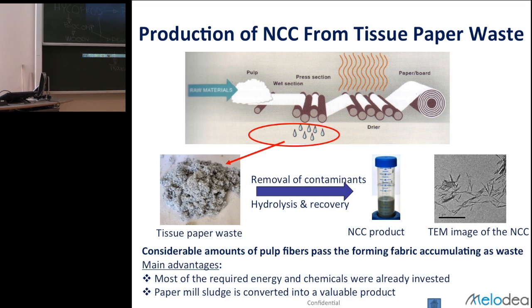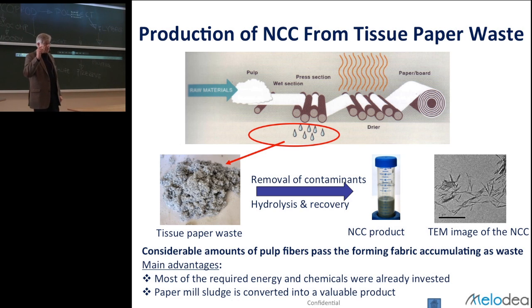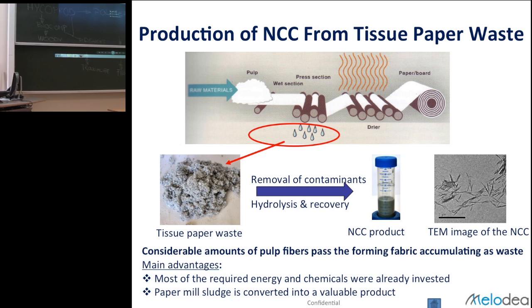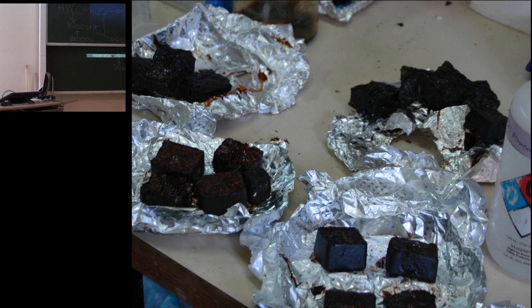So I take that, put it in my mixer, the drink mixer, to make it smaller. And when the drink mixer can't make it smaller, I use sonification, ultrasound. With the sonification, I can make it so small that it turns transparent. It's still a gel inside, but it's completely transparent. And it happens in minutes. And it is that transparent gel that I freeze, take away the ice, and have my foam.